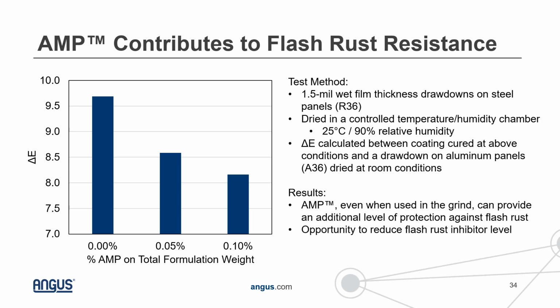And so what we did here was we took a 1.5 mil wet film thickness drawdown on a steel panel, but rather than curing this at room temperature conditions, we cured this in a controlled temperature and humidity chamber. So we looked at 25 degrees C and 90% relative humidity. So this is a very, very harsh curing condition for these formulations. And so all of these formulations that were cured under that condition showed evidence of flash rusting. But what we noticed was that the flash rusting was much less for samples that contained AMP.